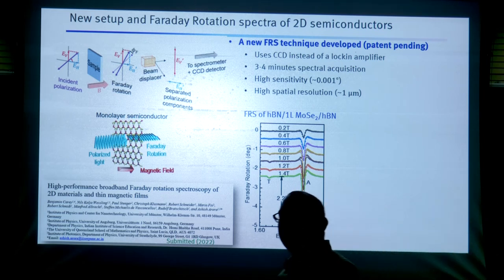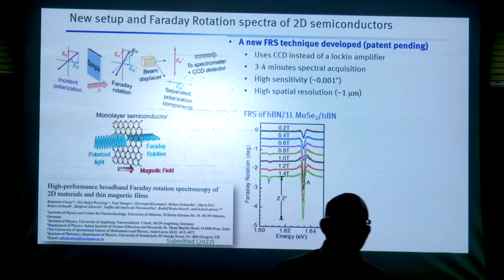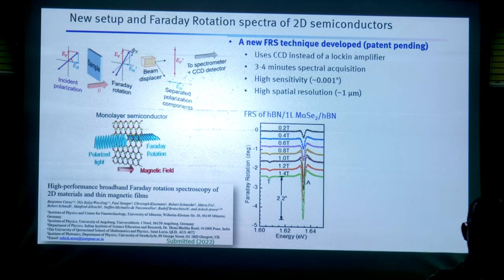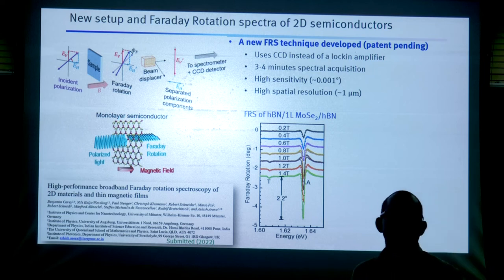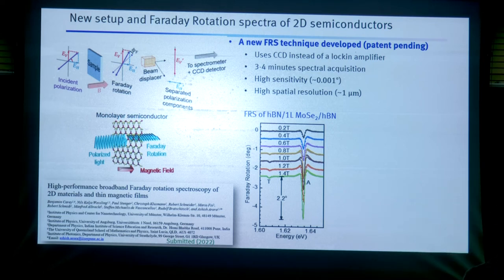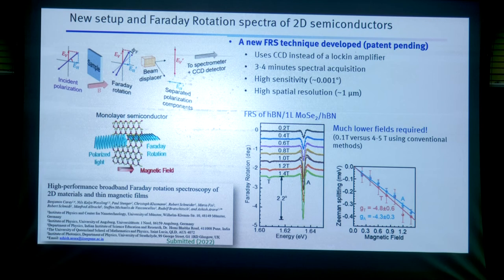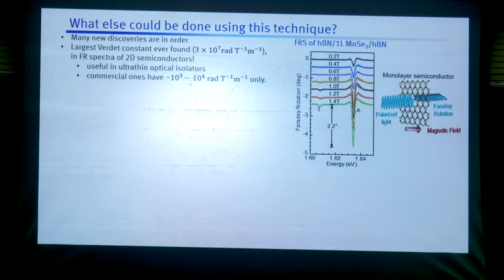Earlier, we had to apply at least 10 Tesla to see all of this, because the signal is very low, the splitting is very low. But now we have improved it by maybe 2 orders of magnitude or something. So this is our innovation. And we can now use this much lower field compared to 4 or 5 Tesla to measure all of the Zeeman splittings and g factors and so on.